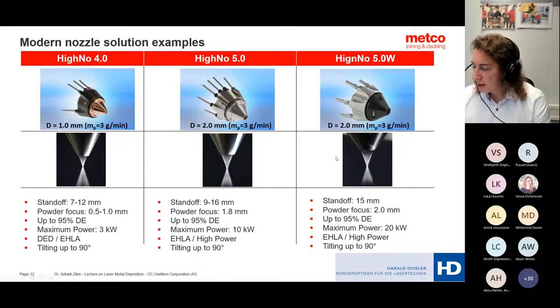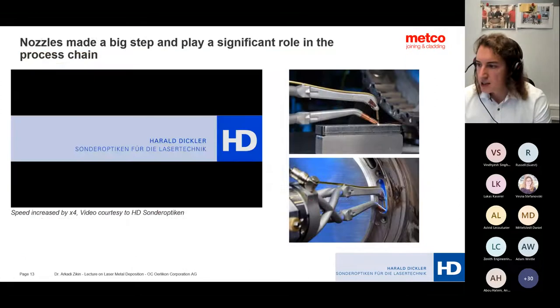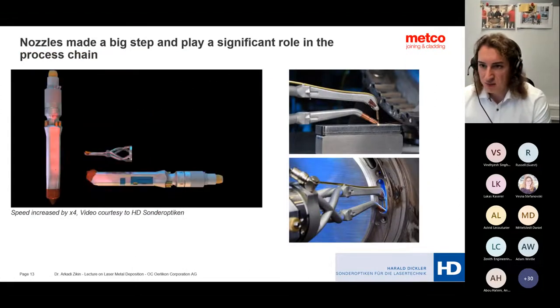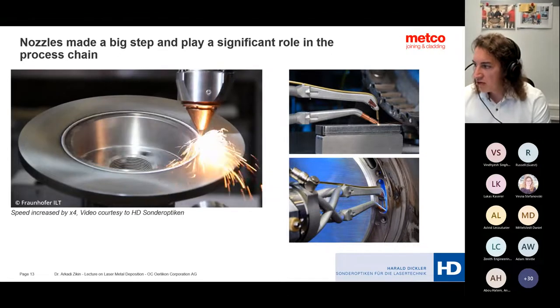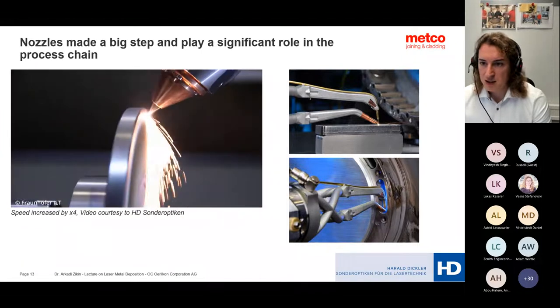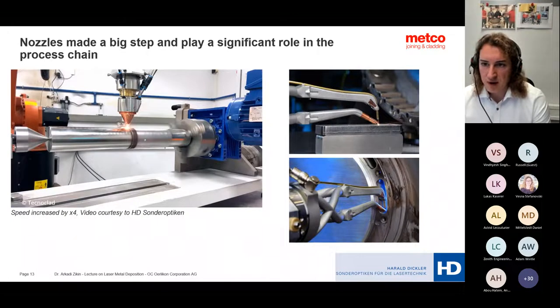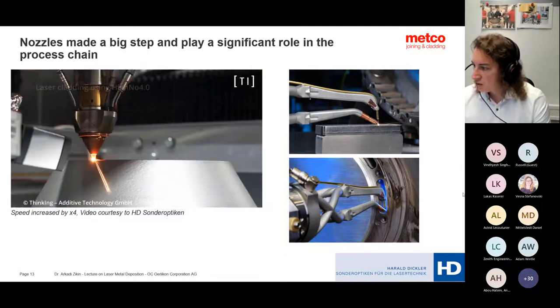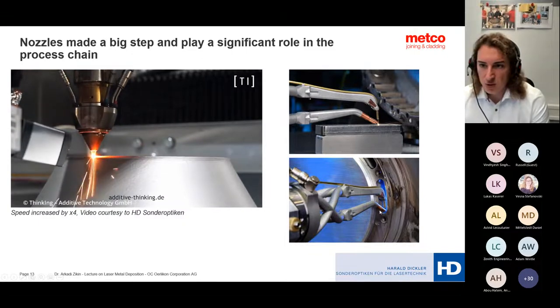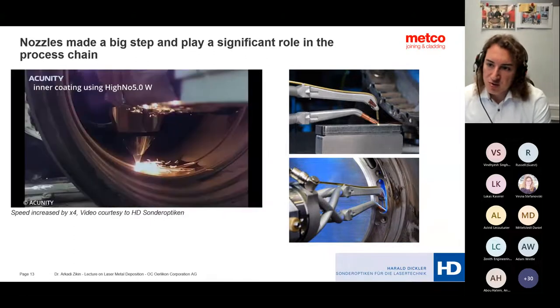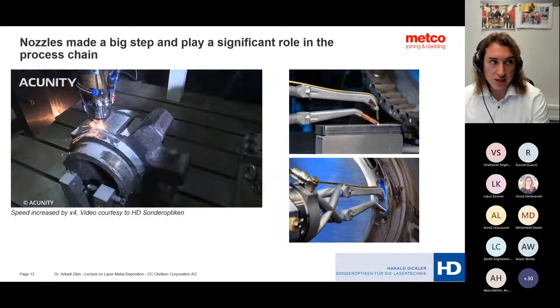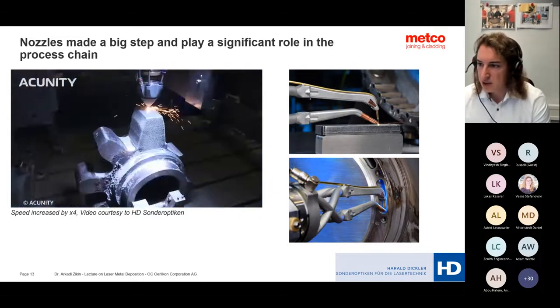If you think about, let's say, 20 kilowatts, which have additional cooling channels within the nozzle surviving under these high conditions. Also, what was a surprise for me, the coaxial nozzle's tilting angle has changed, and those types of nozzles nowadays can work independent from the deposition angle. And some companies go further and develop certain tools and guns which can help you access very complex shapes and work in dimensions and edges where typically you would not be able to repair or protect the surfaces, which might be very important for applications, for example, in marine environments or any other type of applications.